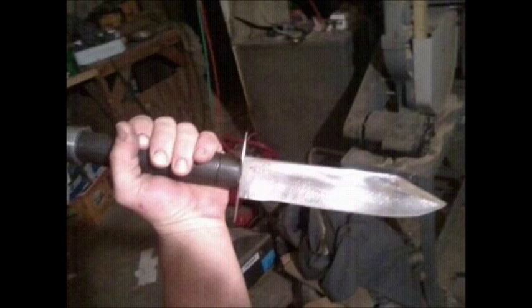Okay, so after I do that, if you want to have the edge hammered in good enough, you flatten it out good enough, I normally would let it sit out for a bit after heating it up red hot. Let it anneal, soften up a little bit. Then I go in for the heat treat, bring it up as hot as I can without melting it, and plunge it into the oil, which I use vegetable oil. It's the cheapest oil I could really get. And once you have that, you inspect it for any cracks and warps in it.